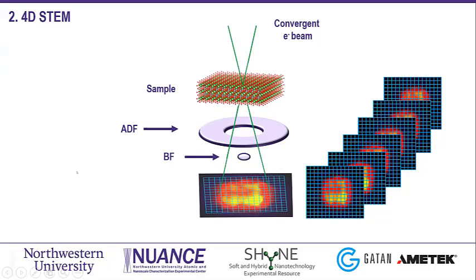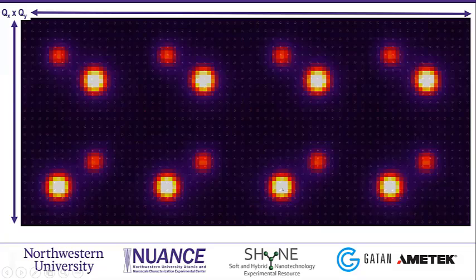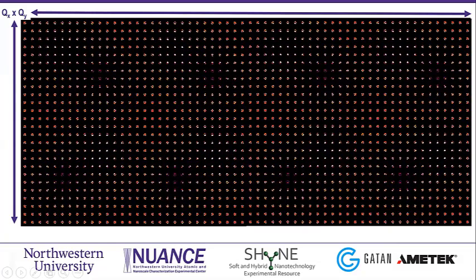I'm going to show you later today during the live demo how you can play with that, and with help of Gatan, you can synchronize. One of the examples is the K2, K3, and One cameras. You can synchronize that with your imaging acquisition, and then acquire a diffraction pattern, your convergent beam electron diffraction pattern, at each probe position during acquisition of your annular dark field image. This is an example here. This would be your final data, right?